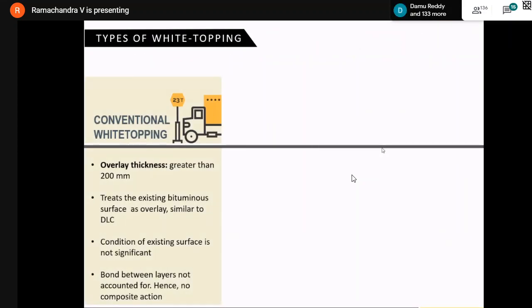If you look at the varieties of white topping, there are 3 varieties. One is called the conventional white topping, where the overall thickness of the concrete surface is 200 millimeters or 8 inches. In this case, it treats the existing bitumen surface below just as an overlay, very similar to dry-lean concrete. The condition of the existing surface is not significant. Don't worry about how much the bitumen road is deteriorated, and the bond between them is anyway not considered. Therefore, this is called conventional white topping.